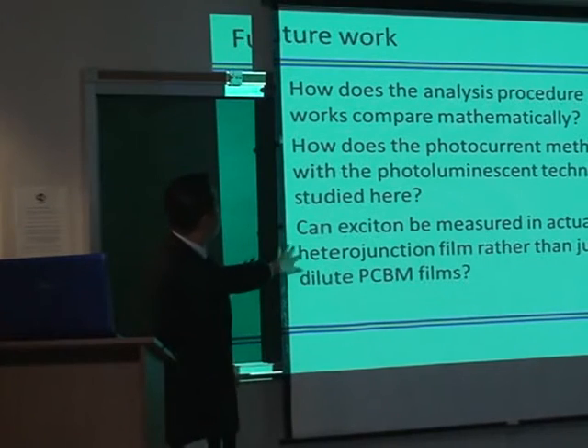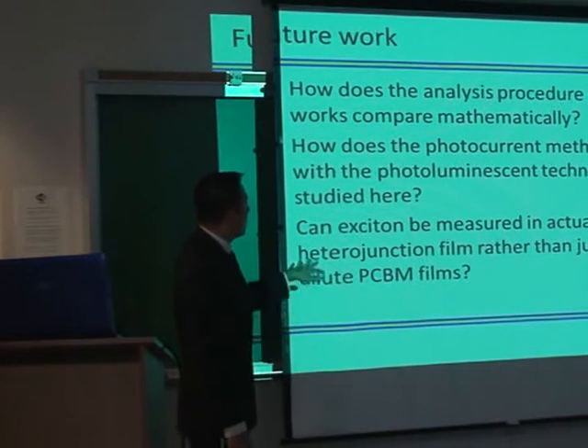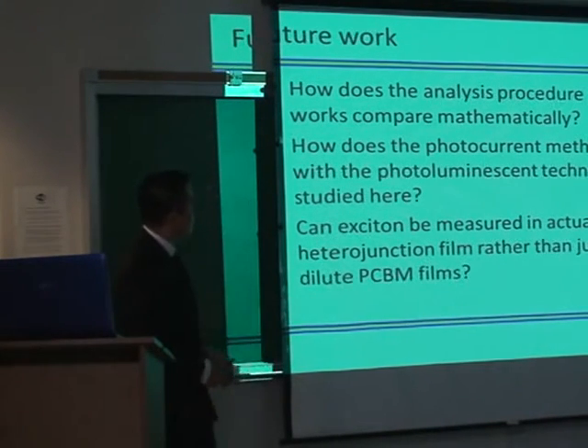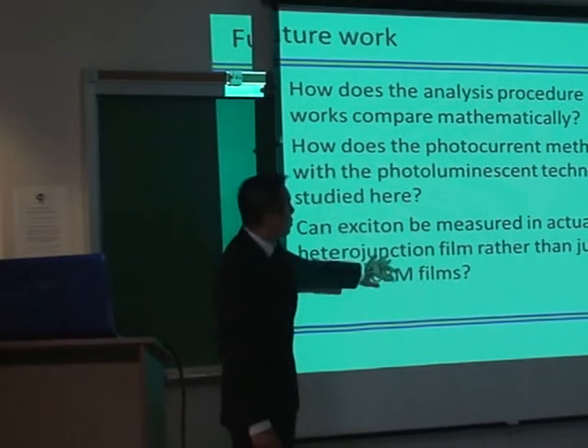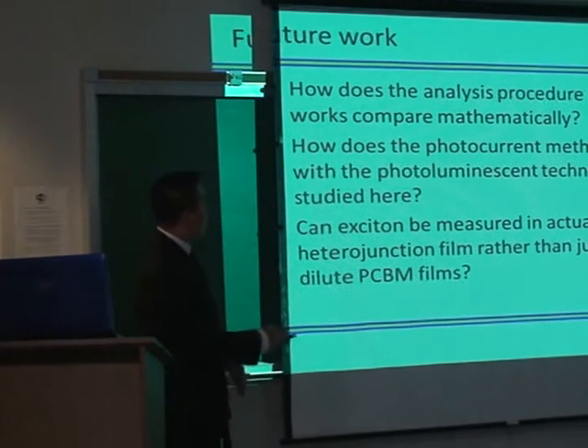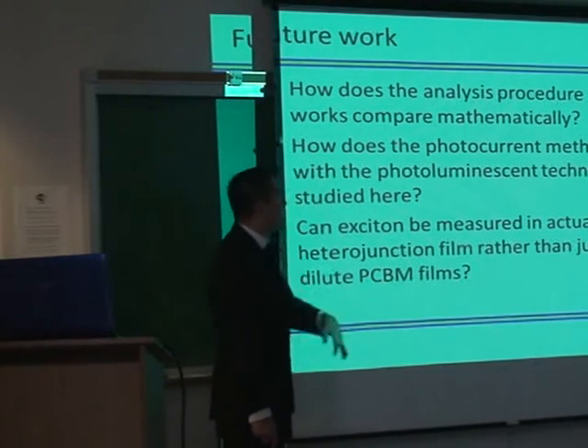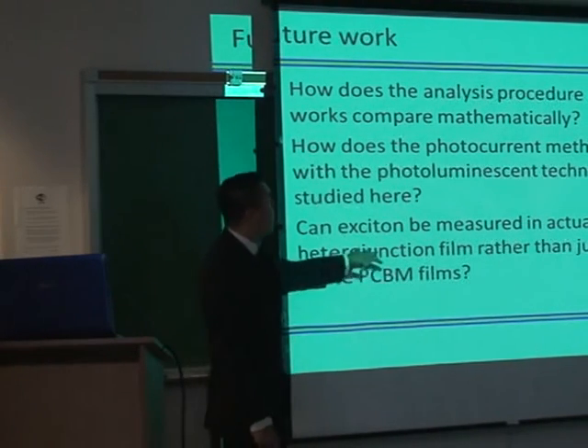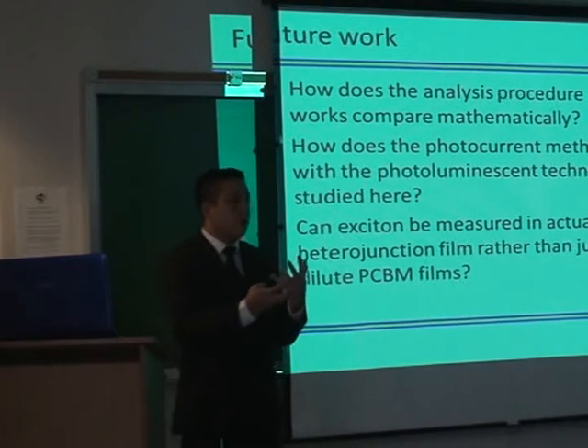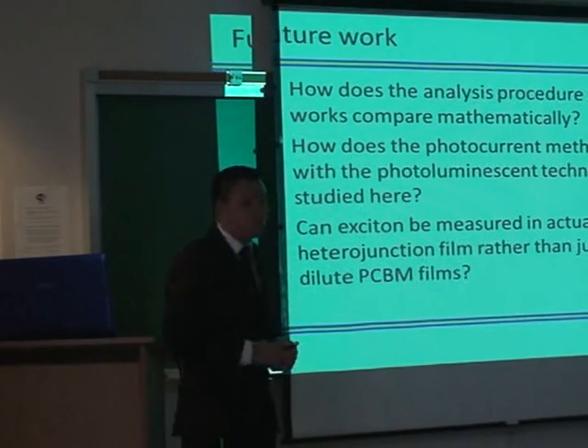And then finally, another question that might be interesting to probe is, can exciton diffusion length actually be measured in a bulk heterojunction film rather than just a bilayer or PCBM film? That's usually the conditions that we probe. But most solar cells are actually a bulk heterojunction. What that means is that the two materials are intimately mixed together.